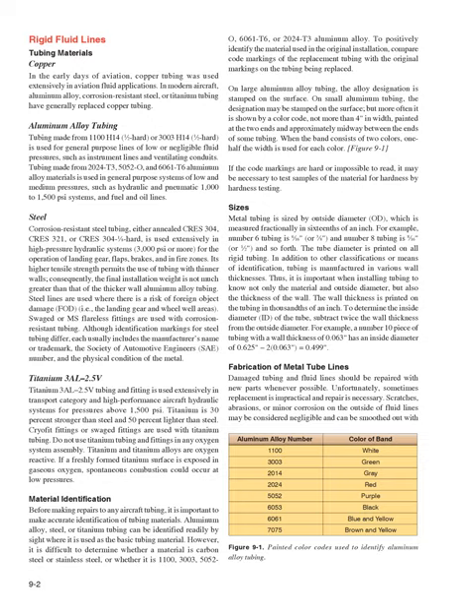Do not use titanium tubing and fittings in any oxygen system assembly. Titanium and titanium alloys are oxygen reactive. If a freshly formed titanium surface is exposed in gaseous oxygen, spontaneous combustion could occur at low pressures. Material identification: before making repairs to any aircraft tubing, it is important to make accurate identification of tubing materials. Aluminum alloy, steel, or titanium tubing can be identified readily by sight where it is used as the basic tubing material.